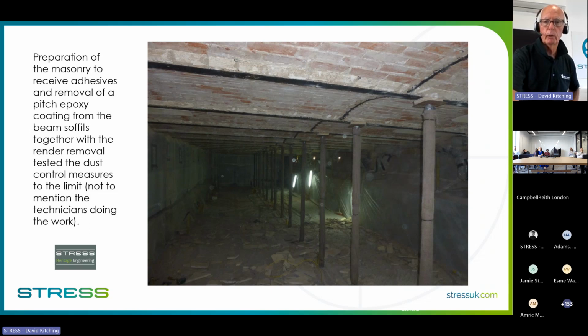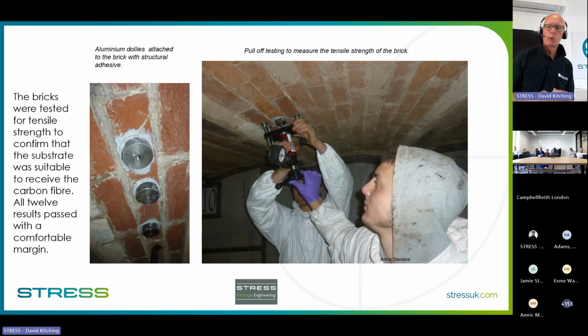So we've got to clean up that brickwork, make sure it's ready for bonding. And the bonding is everything, because if you don't get a good bond to that brickwork, like I've said before, you might as well use duct tape. So we want to mobilize the bond between the brickwork and the carbon fiber, and that is essential. For those of you who don't know, to mobilize the full strength of carbon fiber plate like this, which is 10 times stronger than equivalent steel, you need 1.25 newtons per millimeter squared of bond. And that is enough to fully mobilize the strength of the carbon fiber.